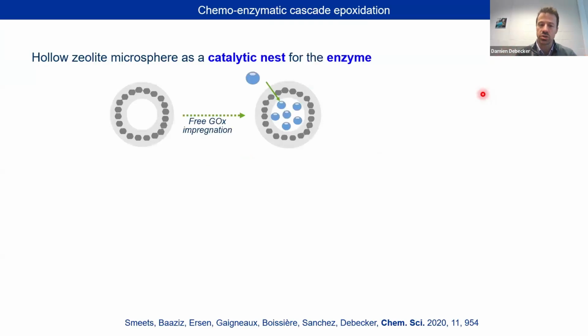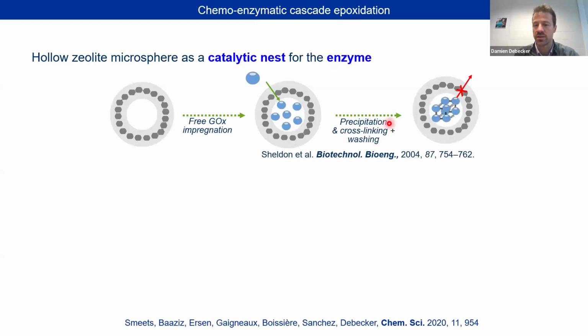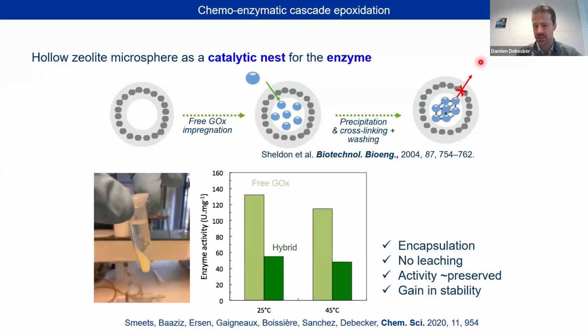Now, what to do with it? We just load it with an enzyme by impregnation. Once the enzyme is in, we wash a little bit, and then we use a strategy based on precipitation and cross-linking to make what we call CLEAs, cross-linked enzyme aggregates. These aggregates are too big afterwards to escape the cages. They stay there, and we have our bifunctional catalyst.